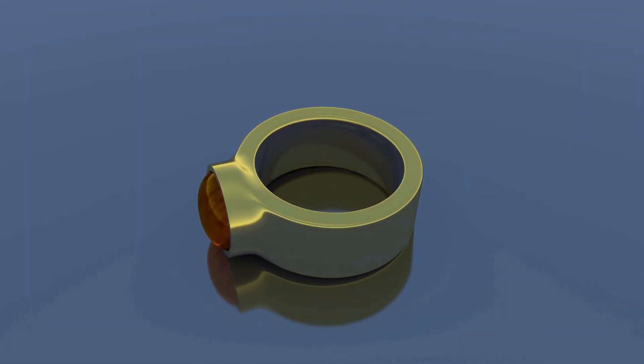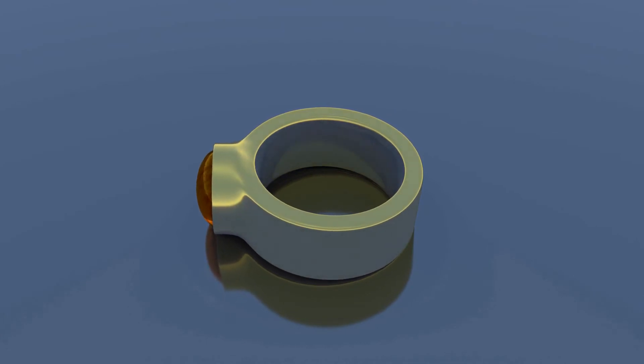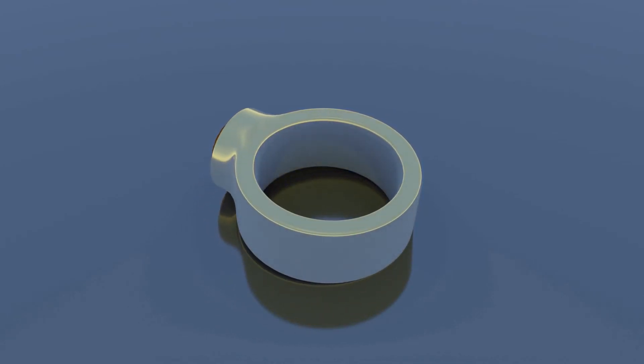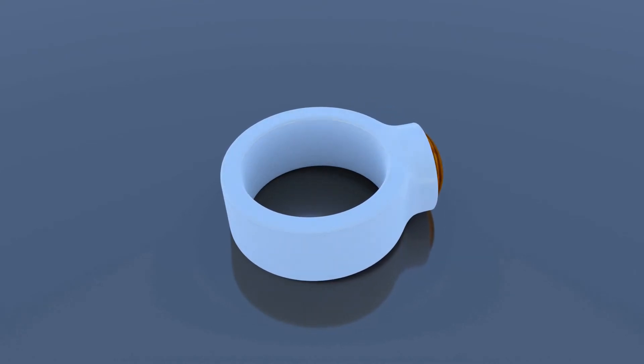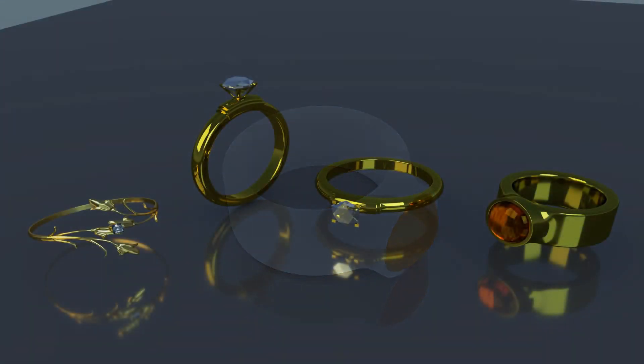High silver content. Silver does not dissolve in aqua regia. It forms an insoluble salt called silver chloride, which can coat your gold, making it difficult for the solution to come in contact and dissolve the gold. Normal silver content in 14-carat gold is 6%. 10-carat and 18-carat have higher silver content. Green gold is also very high in silver.